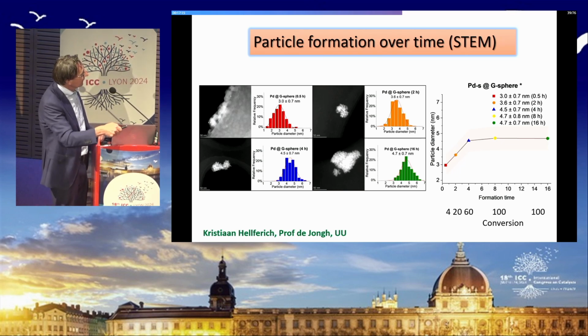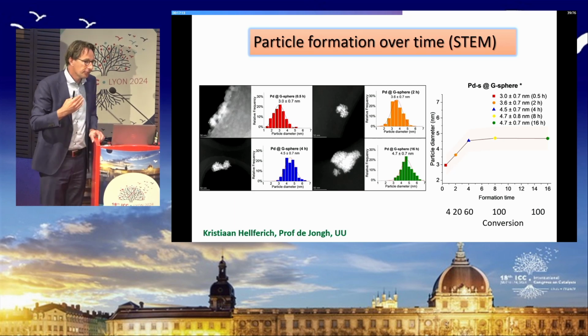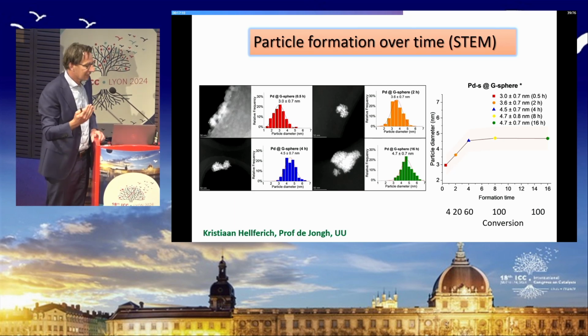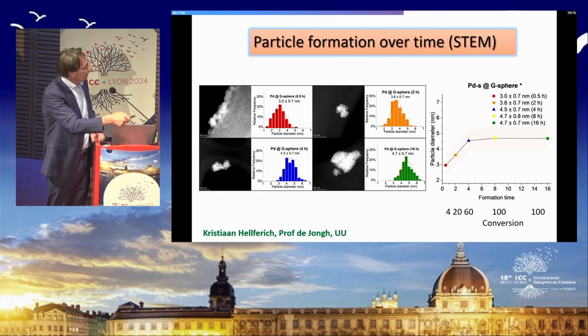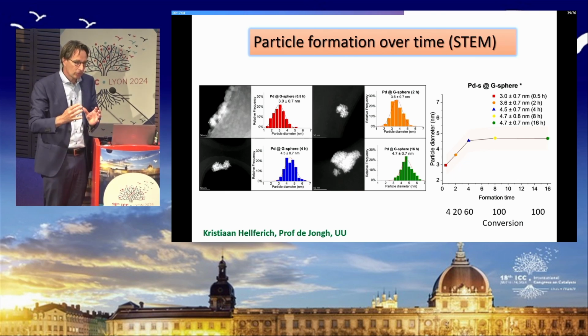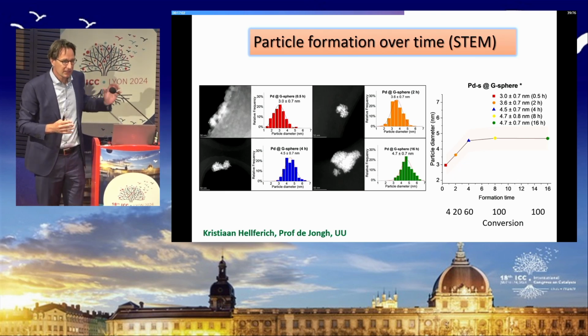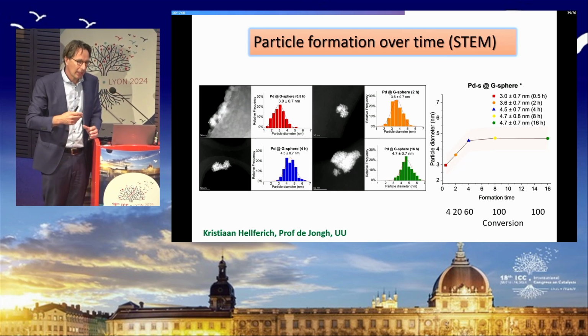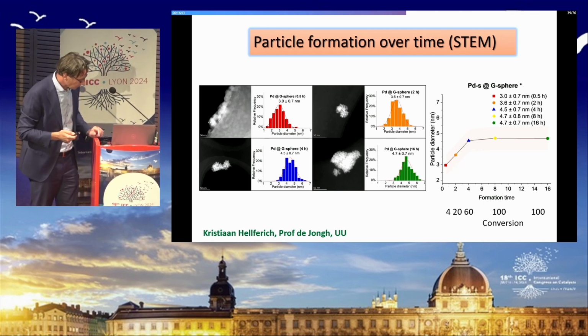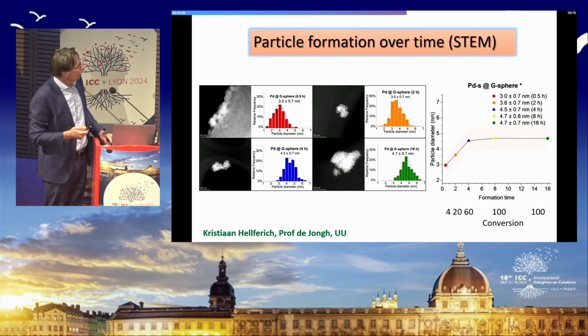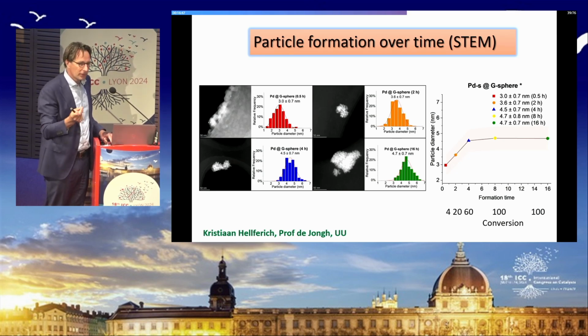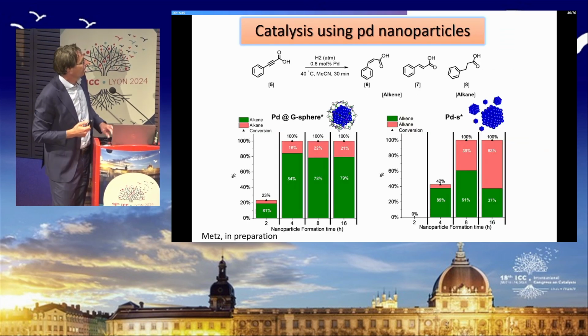And from this plot you can already see that even before all the catalyst or all the complex is converted, we have a very large nanoparticle. So this is in line with a model where you have nanoparticle growth and that catalyst complexes exchange rapidly on the time scale of nanoparticle formation. So clearly there is a disadvantage of using this supramolecular interaction, I would say.